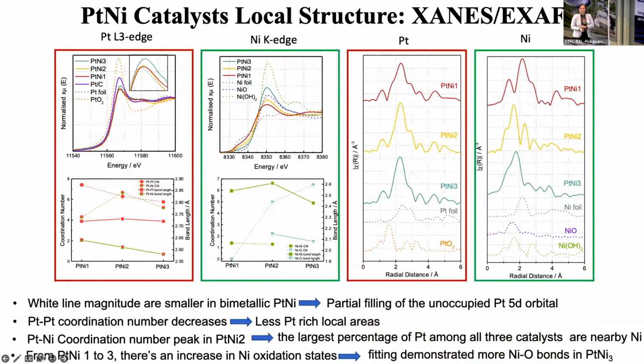To confirm this, we also went and did EXAFS, and pretty much we confirmed indeed that there is a bimetallic product forming because they have a smaller white line magnitude in all this bimetallic platinum nickel. We could see that here we plotted the coordination number for platinum and the nickel, and this is the bond length of different bonds. And we could see the platinum coordination number decreases with increasing the nickel, so less platinum-rich local areas. And we could see that the platinum nickel coordination number in platinum nickel 2 is the highest, which means that we have really 1-to-1 platinum to nickel coordination. And then if we go from platinum nickel 1 to 3, there's an increase in nickel oxidation state. So the more nickel we have, the more prone it is to oxidation and formation of nickel oxygen bonds, which makes sense.